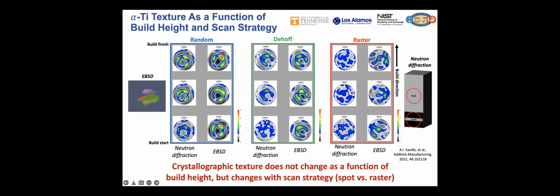Basically, we had slit scans that we did up the build height. And here we're comparing the random and de Hoff spot melt scan strategies as compared to the raster. And it becomes pretty clear that we don't see a lot of texture development from the bottom of the build to the top of the build, but we do see a difference based upon scan strategy. The spot melt strategies look different than the raster.